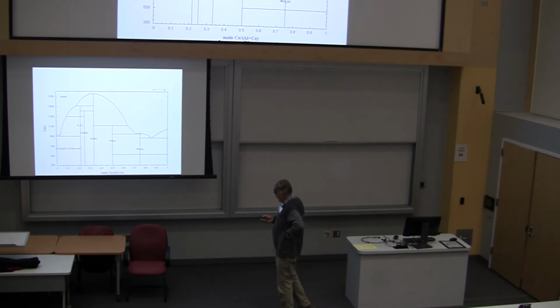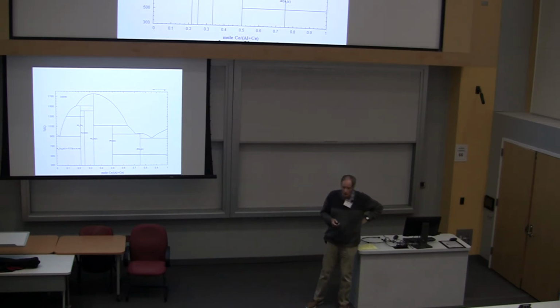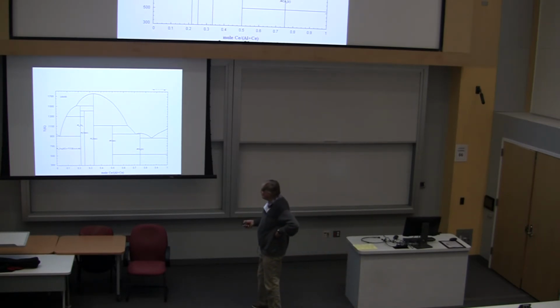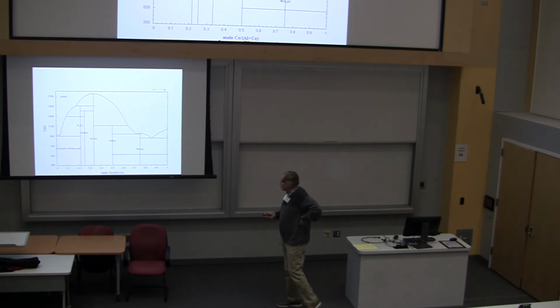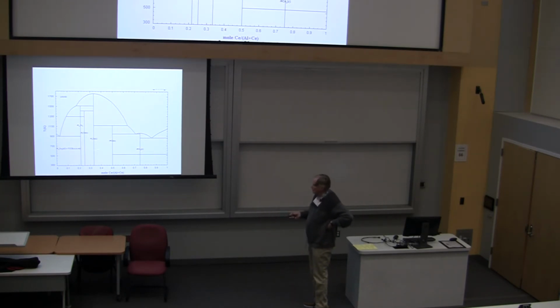One of the original heavy fermion compounds was something called cerium aluminum 3, and here it is inside here. This is cerium aluminum 3, and so you look at this and you say, how can you possibly grow single crystals of this? Well, it turns out this is what you call buried in there, and there's no simple way to do it, and the only single crystals I know of that anybody got were done by strain annealing of an arc melt of this stuff.